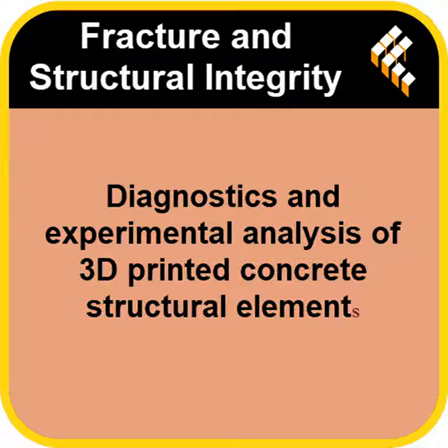Yes. The visualizations really helped rationalize that unpredictability. For the clean, regular columns, the model showed peak stress right where you'd expect, at the bottom. A classic bending crack. Okay. But for the defective columns, the ones with the narrow filaments, the stress was all over the place. Elevated stresses across the wall and even along the upper wall. Which is perfectly consistent with that sudden brittle delamination failure they saw in the lab.